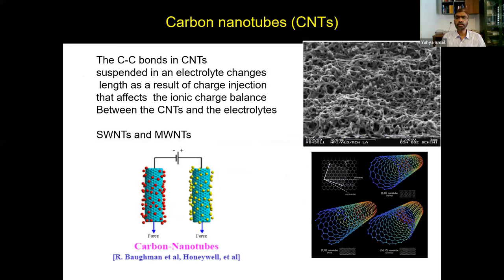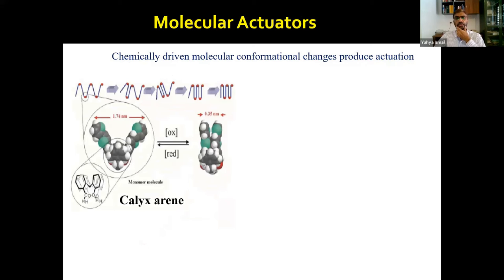Then the fourth one is the carbon nanotube. There are different mechanisms put forward for carbon nanotube. One of the pioneers in carbon nanotube actuation, in carbon nanotube artificial muscles, is Professor Ray H. Baughman at UTD, the Alan G. MacDiarmid NanoTech Institute. He's the director, and he was the first one to produce a carbon nanotube based artificial muscle. The most prominent mechanism put forward is the non-Faradaic charge discharging mechanism. But some other groups are also arguing that there are Faradaic processes, meaning redox reactions, taking place in carbon nanotubes that cause actuation. But the prominent mechanism put forward for the actuation of CNTs is double layer charging and discharging. And the first paper appeared in 1999 in Science on carbon nanotube actuators.